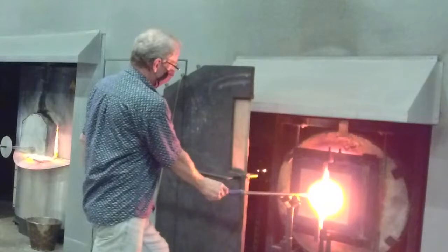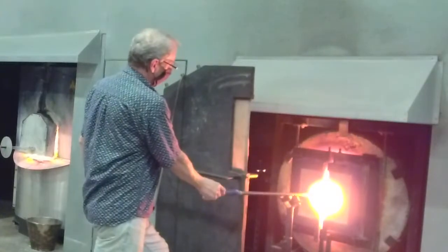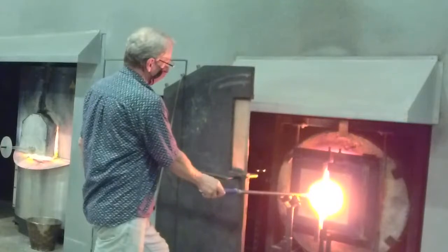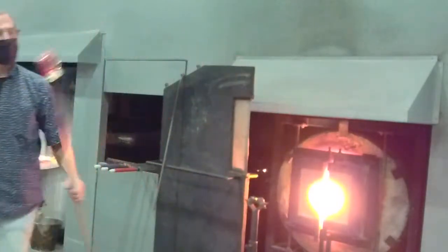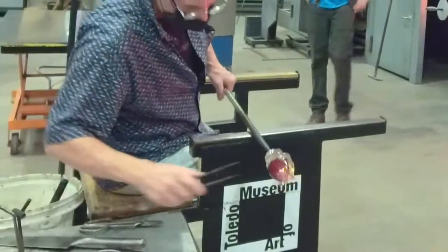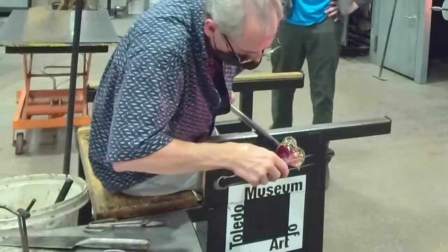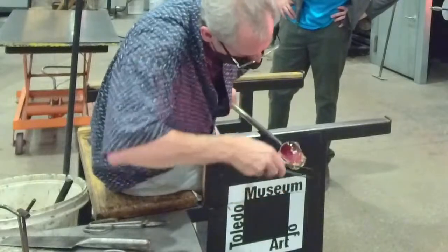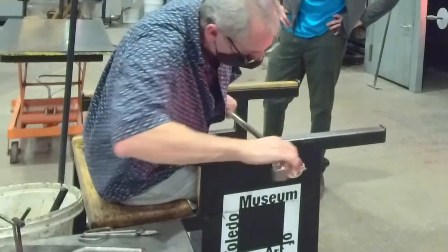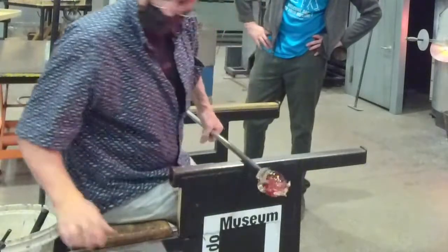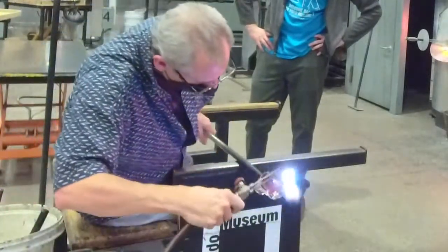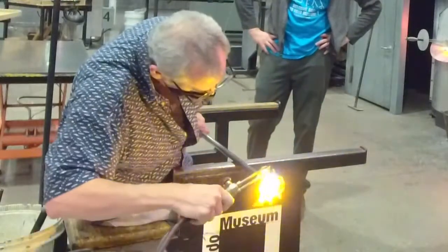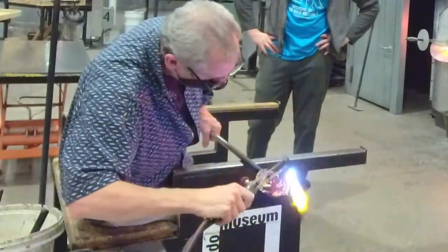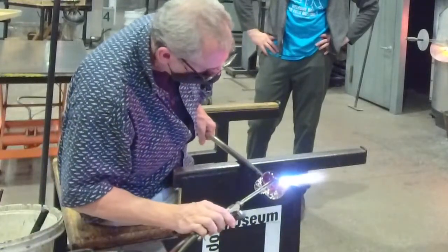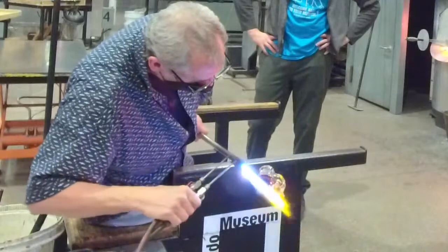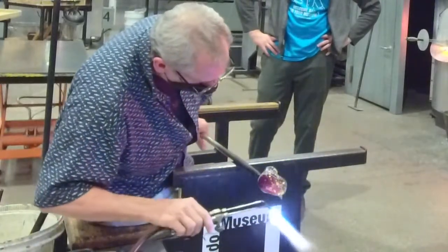Periodically we make sure that the whole form is what we call flashing, to bring it back up to an atmosphere that's closer to hotter than it is colder, because glass in the outside atmosphere cools down at a very quick rate. So if we do not constantly reheat the glass, it will shrink on itself and crack. This glass, when it's hot, actually expands a little bit, not by much, but enough that that's why it moves. But as it gets cooler, it will contract on itself while it's still hot on the inside, and that's what causes the glass to crack.